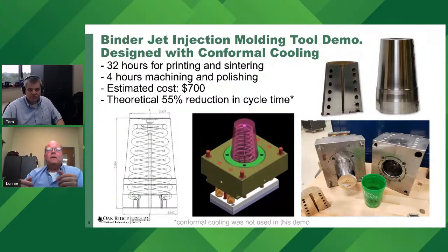You don't have to wait to get the billet. You can go straight from powder to your near net shape, independent of the geometry. The powder doesn't care. You're building it up layer by layer. So you go direct to printing from your feedstock, then sinter it, then back infiltrate it, and then machine it. You can get your tool, and instead of 6 weeks, you can do it in a couple of days. Next slide.